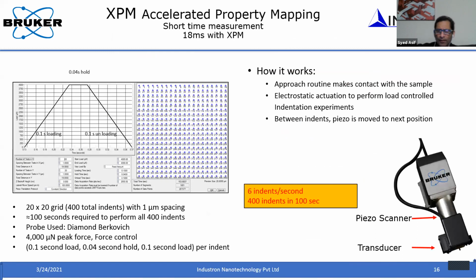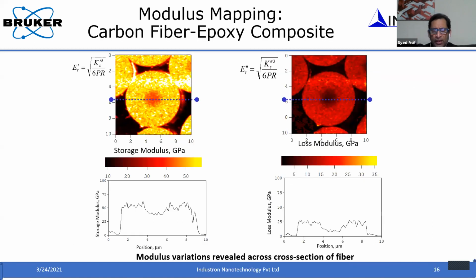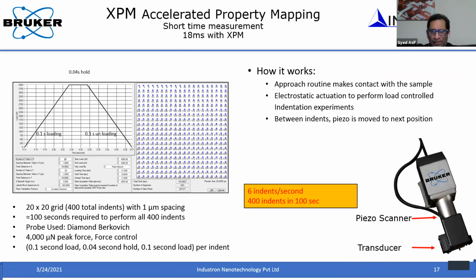Now, the previous experiment that I mentioned is only applicable for measuring the modulus of the material, because we are making a very light contact with very small force. There is no plastic deformation. So the information that you are getting is the elastic response or the viscoelastic response of the material. It doesn't allow you to get the plastic deformation of the material. But you can do that by doing indentation, but in a very rapid way.